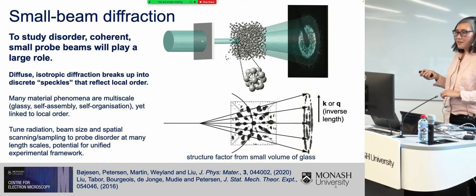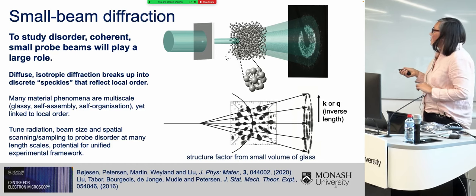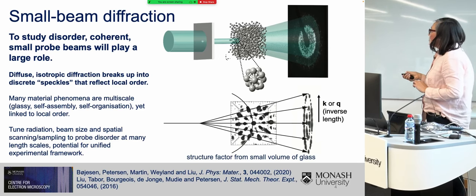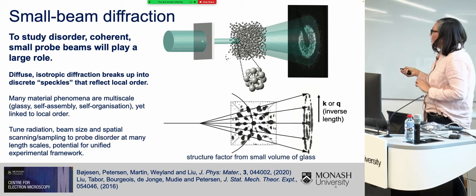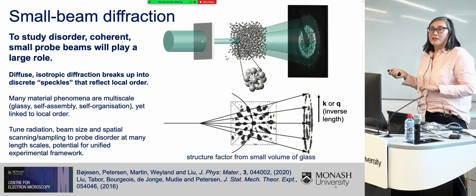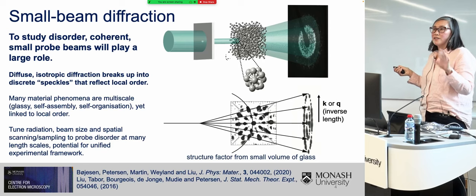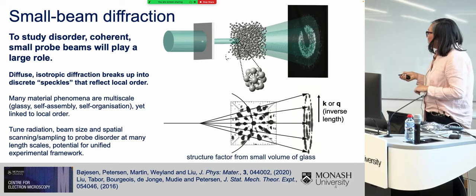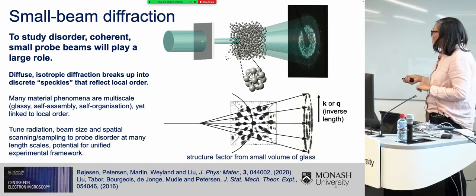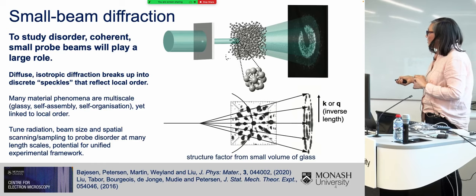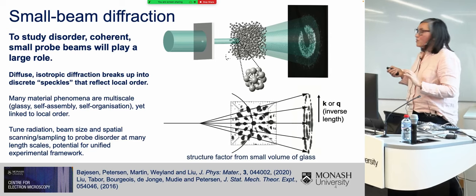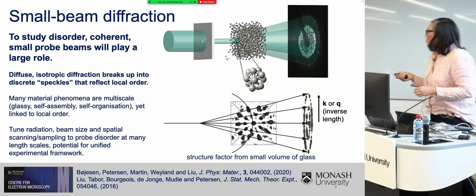So I believe that to study disorder, coherent small probe beams are actually going to play a very large role. So you can see here, when I restrict the size of my beam to the size of some relevant correlation length in the material, in this case, a coordination polyhedron, the diffuse and isotropic diffracted intensity from a disordered material actually breaks up into these discrete patches of intensity that we call speckle. And here you see down here where I've calculated the structure factor in three dimensions from a small volume of glass. The structure factor has broken up into these discrete patches, and where it's cut by the Ewald sphere, we get projected intensities in our measured diffraction pattern. And these intensities actually contain information that's strongly linked to the local order in the volume that we probe.